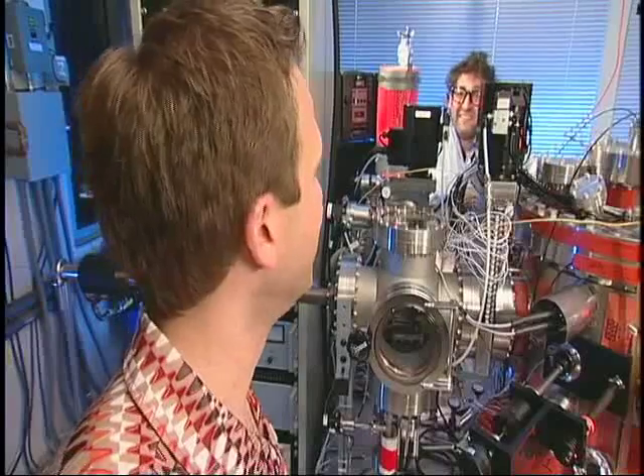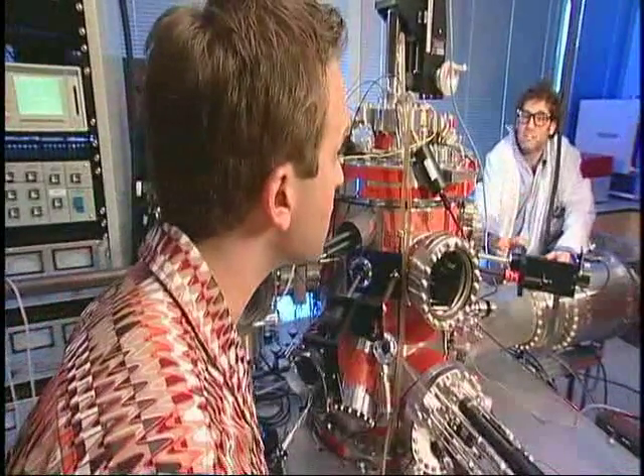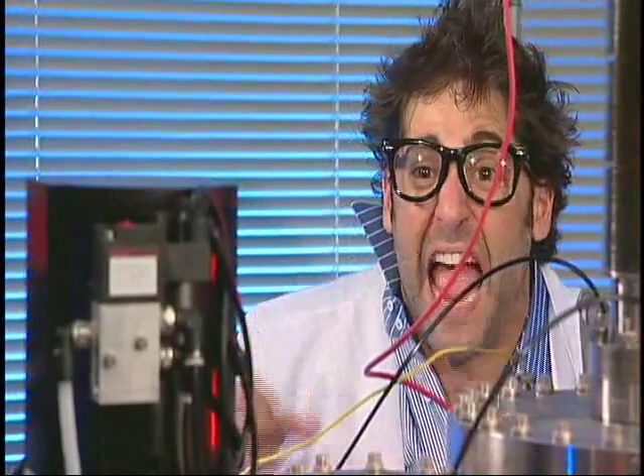I have just transferred an array of our latest nanostructured chemical field effect transistor devices from the load lock into the ultra-high vacuum section of the molecular beam epitaxy machine here, the MBE. Oh, that's what I thought. And then what are you going to do? The devices will be coated with a number of metallophthalocyanines that contain bulky substituent groups to help us achieve a desired microstructure. I'll be coating the individual elements of the array using a floating shadow mask positioned within 10 micrometers of the array. The mask will be moved in situ without breaking vacuum, exposing one array element at a time.